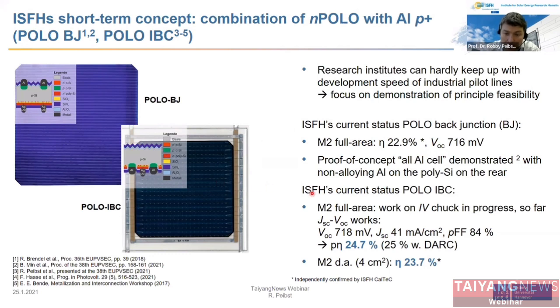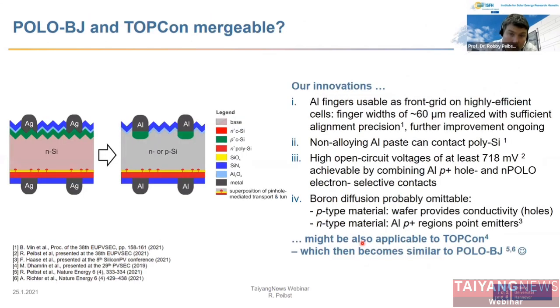We're still struggling with the precise measurement of our fill factor. That's why we can only report on the other parameters and only report these pseudo efficiencies of 25%. Nevertheless, on a designated area, we have a confirmed efficiency of 23.7% from ISFH CalTeC, which is also, I would say, fair, not record level.